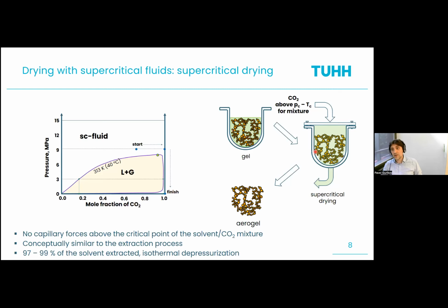So basically, we take a gel which contains a liquid which is miscible with CO2, with carbon dioxide, because carbon dioxide has a very moderate critical temperature and critical pressure. And many solvents are miscible with CO2, and they form supercritical mixtures. And that gives us a fantastic way to extract the solvent, which is depicted here as green, with CO2 working just above the critical pressure and critical temperature for the corresponding mixture. So that's how you bring this high temperature supercritical drying into the so-called low temperature supercritical drying, the process we use extensively now to produce porous materials out of gels.